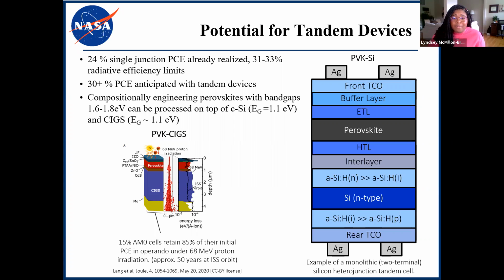Now, wide bandgap perovskite top cells and low bandgap bottom cells can include another perovskite, or crystalline silicon, or copper indium gallium selenide, or CIGS, bottom cells. And these are all suitable materials towards realizing the goal of low-cost tandems that would also be suitable for operation in space. And on the bottom left, I have an image taken from a paper published by Lang et al. And here they have generated perovskite CIGS tandems, and they perform at 15% in AM0, which is the solar spectrum in space. And they actually retained 85% of their initial power conversion efficiency during operation, while they exposed these cells to about 68 MeV protons.